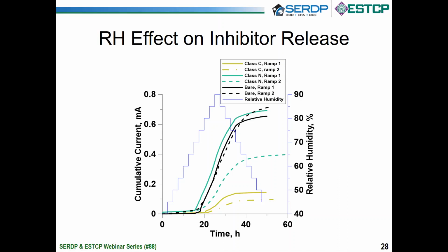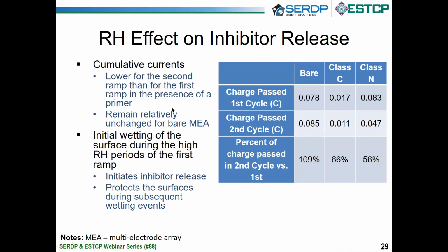So, and this may explain some of the phenomena that we see in accelerated corrosion with non-chromes. There always seems to be some staining in the scribe, and this is particularly true for accelerated corrosion tests. Okay. So to summarize that, looking at the cumulative currents, you see these big knockdowns. So you need some kind of initial wetting before you can release these inhibitors, and then you protect the surface during subsequent wetting.